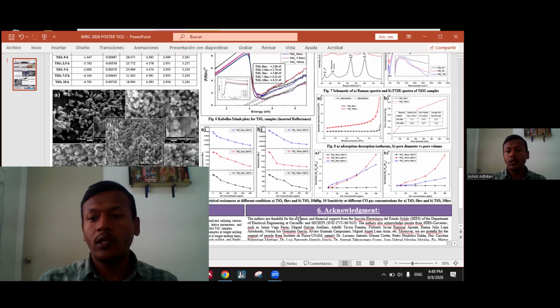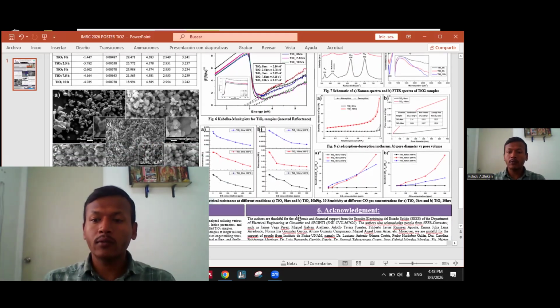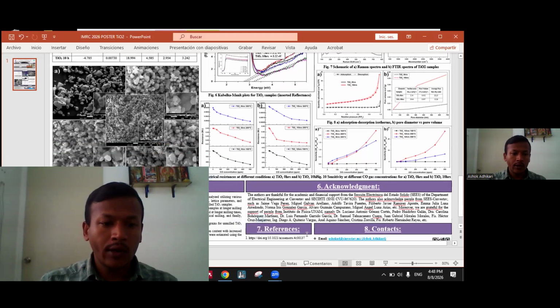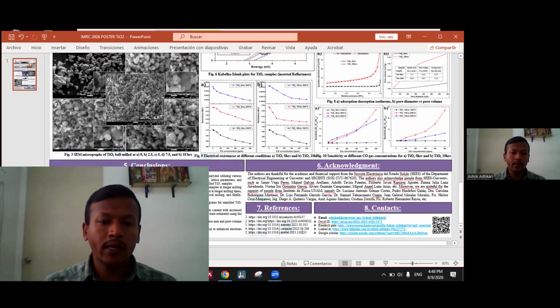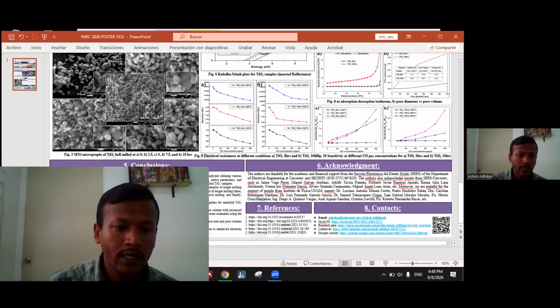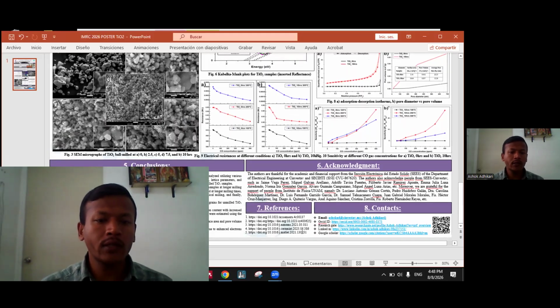So from these results, we can confirm that TiO2 nanoparticles were synthesized by the mechanical process, and their properties were studied utilizing various characterization techniques for their application in CO gas sensors. The structural properties such as XRD peaks, lattice parameters, and interplanar distances confirm the presence of the tetragonal crystal structure, which corresponds to the anatase phase for both milled and unmilled samples.